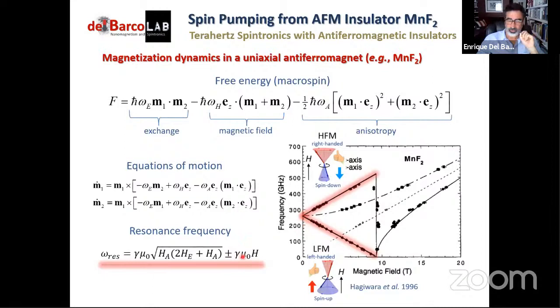So there is a fundamental mode in an antiferromagnet, degenerate, that has high frequency. In manganese difluoride it is 260 gigahertz. In iron difluoride, for example, it is higher than 1.1 terahertz. I believe it's 1.4 terahertz or something like that. But then when we apply a magnetic field, the Zeeman interaction actually breaks the degeneracy between two different antiferromagnetic modes.